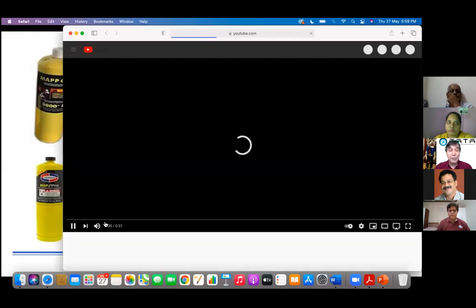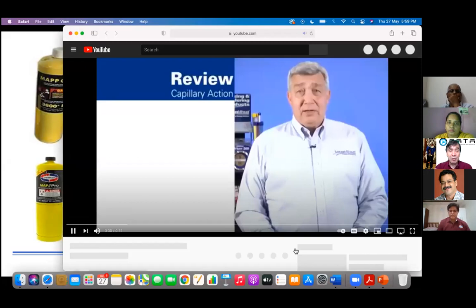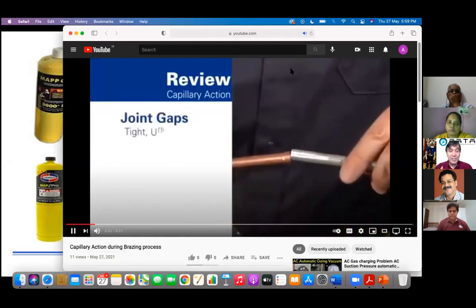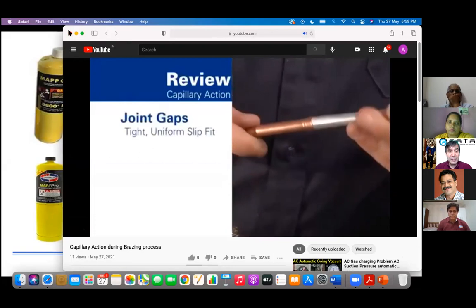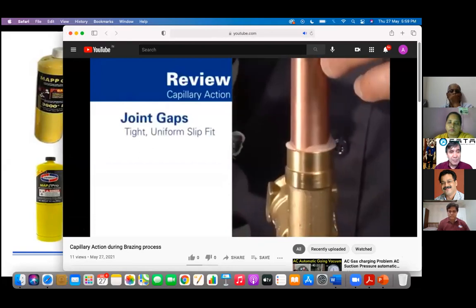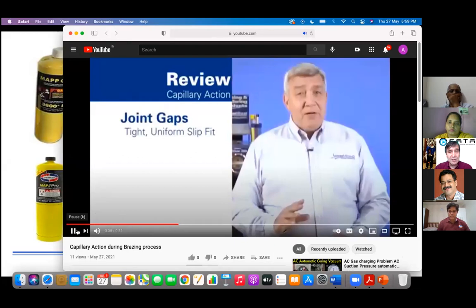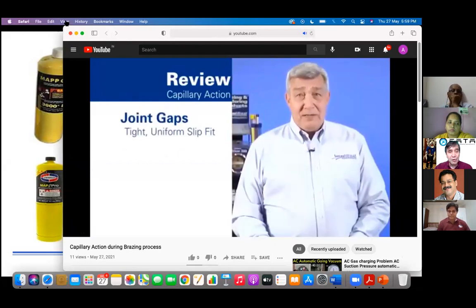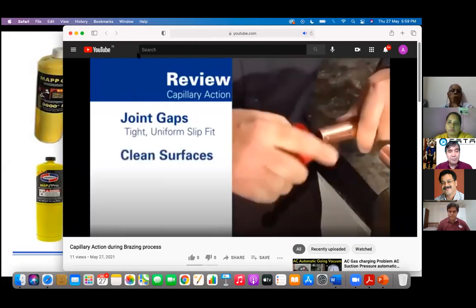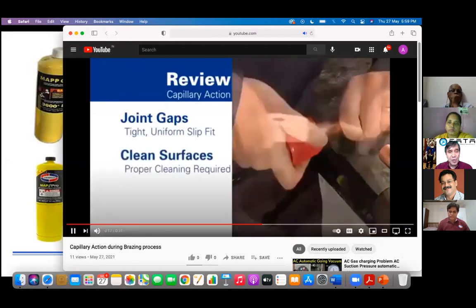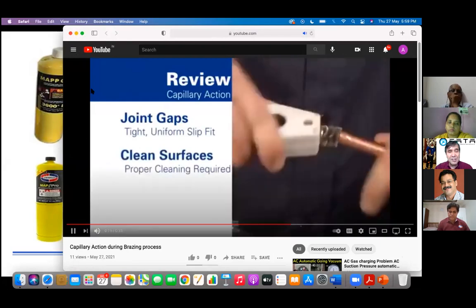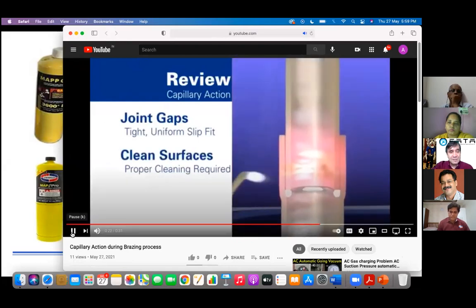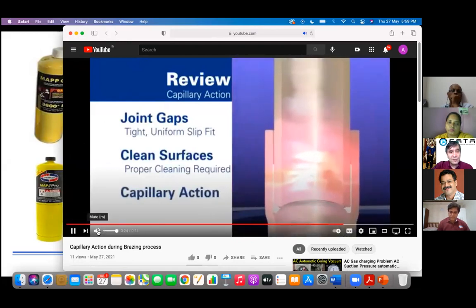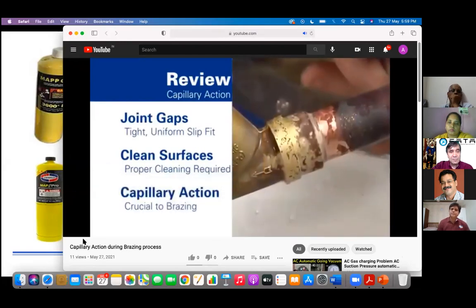And when you have a weak joint, any vibration is going to loosen it, and you end up with refrigerant leaks, which are very costly. Variation in spacing will affect the success of your brazing operation, because capillarity will be compromised. Second, cleanliness counts in brazing. Parts that are not properly cleaned may carry grease or other debris, which will impede capillarity. Successful capillary action, the process that allows alloys to flow into the joint between two metal parts, is crucial to successful brazing.